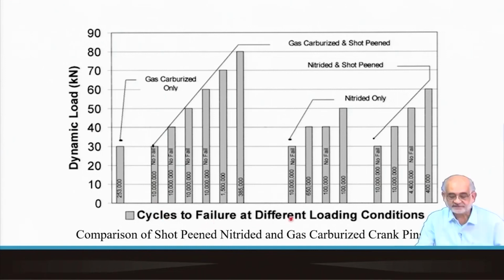So this is the number of cycles to failure needed for various loading conditions, and the materials in use are nitrided or gas carburized pins. As you can see, as you do gas carburizing, this is the number of cycles at a particular given load that one can withstand, and this is for the gas carburized condition followed by shot peening, and this is only gas carburized. So obviously this dual processing, please remember, gas carburizing produces martensite, which also produces residual compressive stress on the surface. So on top of that, if you also do shot peening, you get the highest dynamic load bearing capacity.